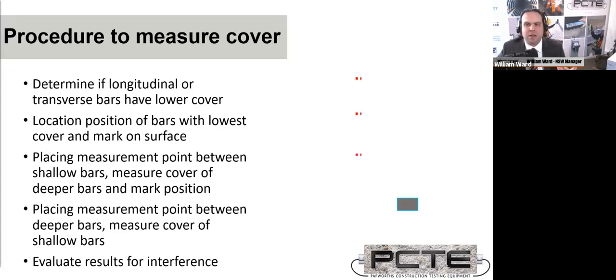So we know the layout of the bars in that direction. At this point, we are not recording cover depth measurements because we haven't set up our machine and we haven't got our layout yet. We can then pass the measurement point of our probe in between those bars. If those bars were more than 150 mm distant, you could then record those lower bars, the bars with more cover, and use those as actual cover depth measurements. We can also join those up. So now we've marked the whole reinforcing layout on the surface.